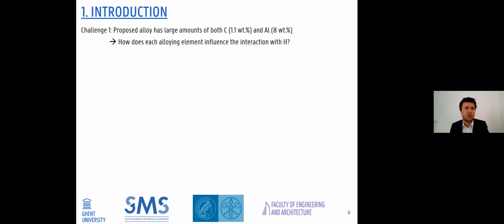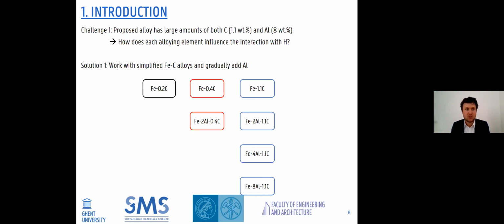A few challenges were faced. The proposed alloy contained quite a large carbon content and aluminium content, as already explained. Now the question is, how does each element influence the interaction with hydrogen? Our approach was to do this in a systematic way and to work with simplified iron carbon alloys. So this was our solution, and we did not only target one material, we did a bunch of alloys, and we evaluated both the influence of carbon and the influence of the addition of aluminium.